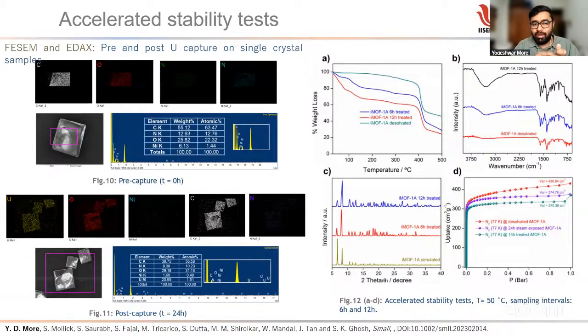We went to the core of the crystal and did the same analysis, to identify whether uranium was on the surface only or deeply diffused within the crystal. After breaking the crystal, we found that the uranium is within the crystal as well, diffused well inside. Such a loaded crystal is also subjected to different characterizations like PXRD, then FTIR to see the changes, then adsorption.